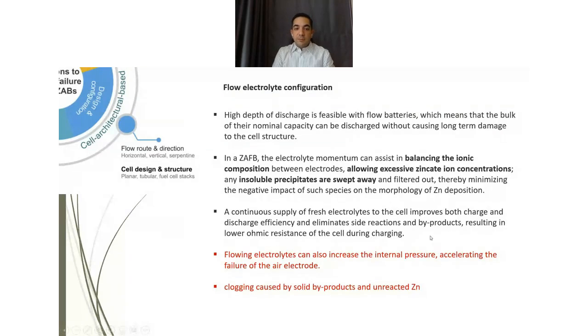But there are also some negative aspects when using the flowing electrolyte system, which is that the internal pressure of the cell will be increased due to the pressure induced from the flowing electrolyte, which in some cases can end up with the failure of the electrode, and also the clogging caused by solid by-products and unreacted zinc. So since the electrolyte can also sometimes carry some solid particles with itself, it can cause clogging.